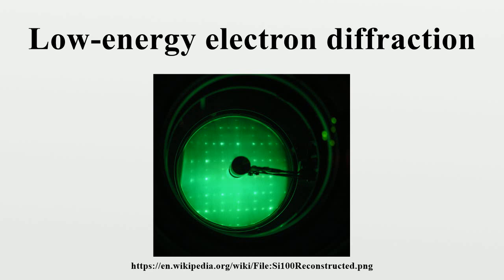In the early 1960s, LEED experienced a renaissance as ultra-high vacuum became widely available and the post-acceleration detection method was introduced. Using this technique, diffracted electrons were accelerated to high energies to produce clear and visible diffraction patterns on a fluorescent screen. It soon became clear that the kinematic theory, which had been successfully used to explain X-ray diffraction experiments, was inadequate for the quantitative interpretation of experimental data obtained from LEED.